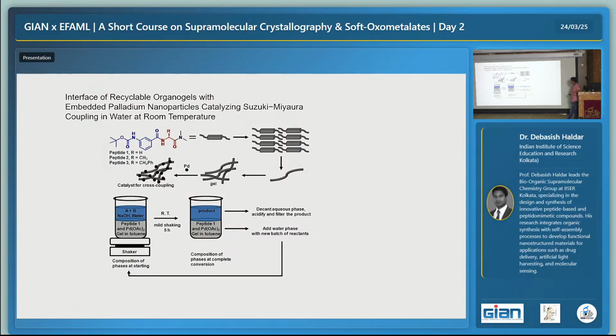And for that purpose, we developed this peptide. It again contains meta-aminobenzoic acid. Here we have a natural amino acid, whether it is glycine, alanine, or phenylalanine. And then at the end, we have the C-terminus N,N-dimethylamine as the capping agent. The peptide is supposed to form this sheet-like structure. It will form fiber, and fiber will form gel by restricting solvents. And then we thought, can we use palladium nanoparticles inside the gel matrix, so that the entire gel matrix can be used for cross coupling reactions, like the Suzuki coupling reaction?